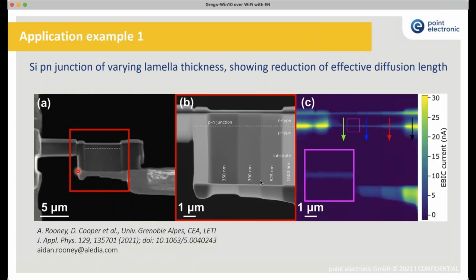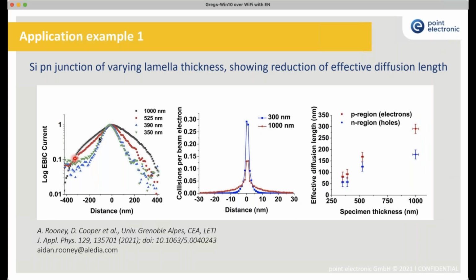If you take a line across this profile at different thicknesses and plot it in semi-log, you can see this diffusive decay, and that's related to the diffusion of minority carriers. So we can measure from this the diffusion length of minority carriers. In this case, we know that the material is quite high quality, so the diffusion length is quite long, more than a micron, but we can see that it's limited by the thickness of the lamella to a much smaller diffusion length. In other words, there isn't space for the minority carriers, whether electrons or holes, to move around. That's in effect induced by the lamella, and this is one reason why we get higher resolution in EBIC in the TEM than in the SEM.